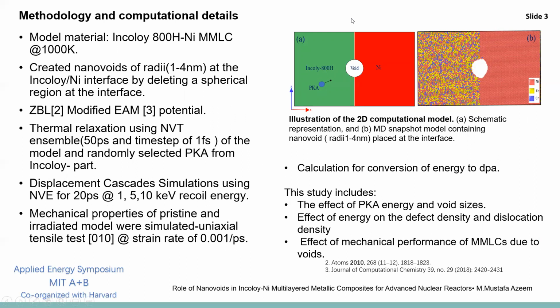We constructed our model by having the initial composition structure by taking FCC lattice nickel at 1000 K, and later we embedded the iron and chromium into the model with the concentration of 47% and 21%. Later periodic boundary conditions were applied in all directions. We used the many body potential, which is more realistic than other potentials, superimposed with the ZBL potential to perform the displacement cascade simulations.